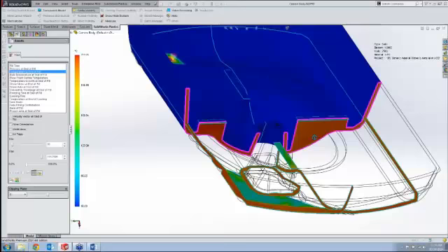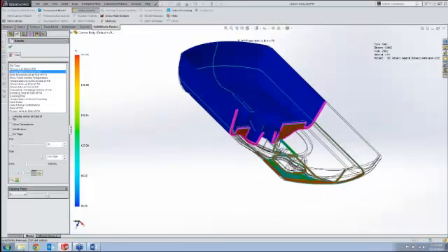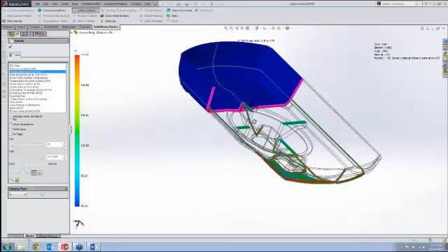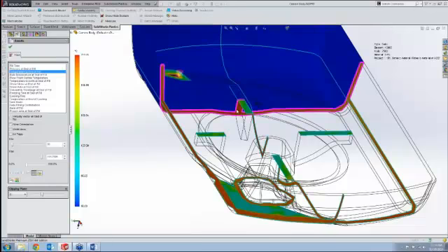You can move these clipping planes to be able to see various areas throughout the model for your interest, see where you've got heat built up inside of the process. And exactly how hot things are at the end of fill are important, but even more so in our professional level package, you'll see at the end of the packing phase, they're even more important because that's when you're going to release the part from the mold. So we're looking for more uniform temperature cooling by the end of pack as well.